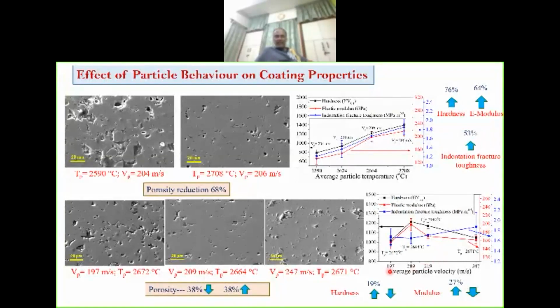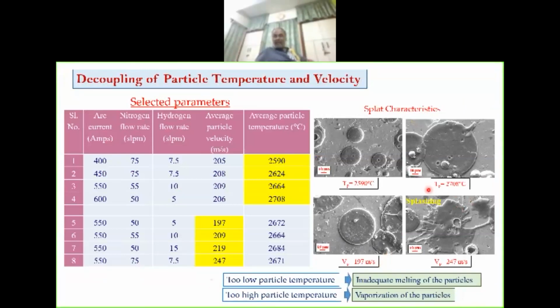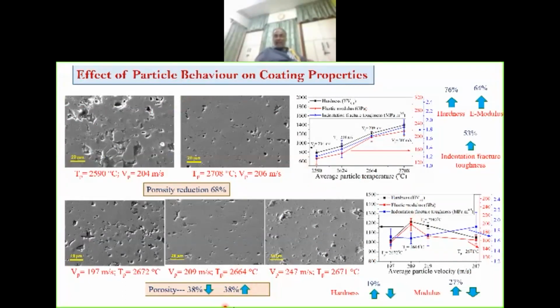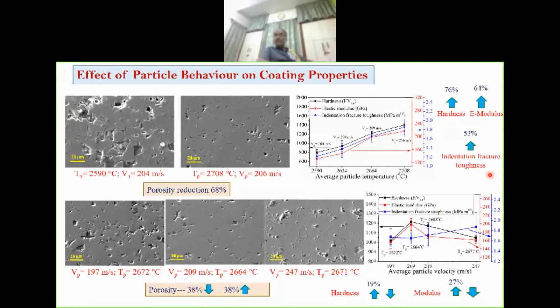Similarly, with increase in velocity, initially porosity decreased because of good particle shape. But when you increase velocity too much, as shown previously, we get a distortion in the splat shape and we get an increase in porosity. Hardness also initially increases, but with porosity it decreases. Same thing goes for modulus of elasticity. So temperature and velocity must be decoupled so that we can get rid of the baggage of parameters, and they should be closely monitored. This process requires very stringent process control.